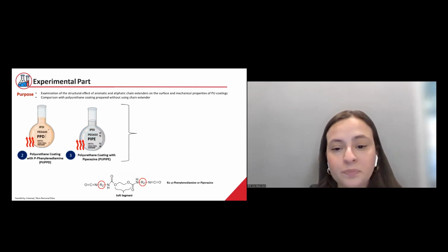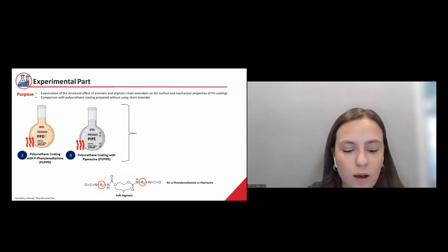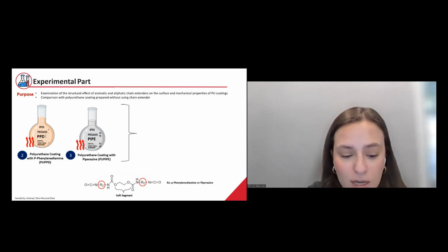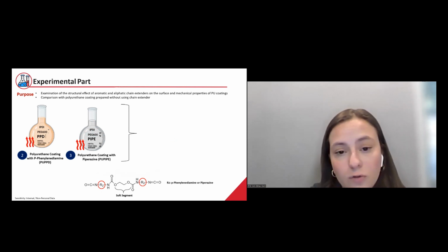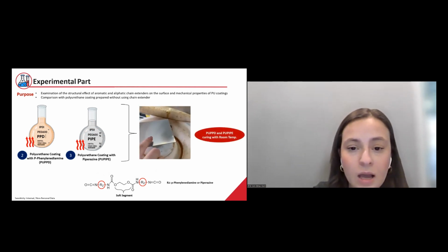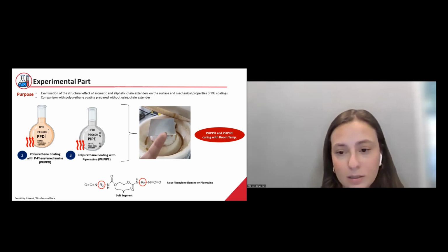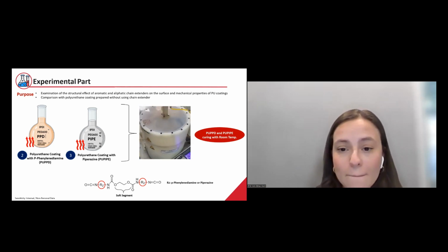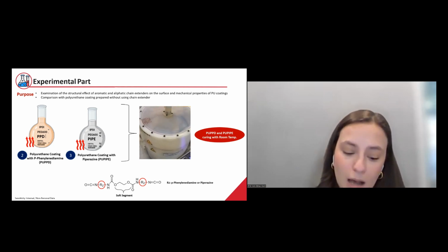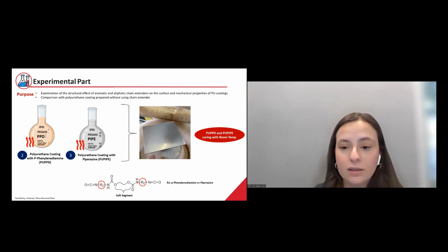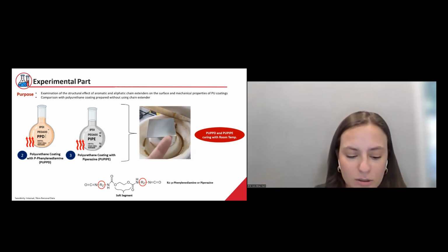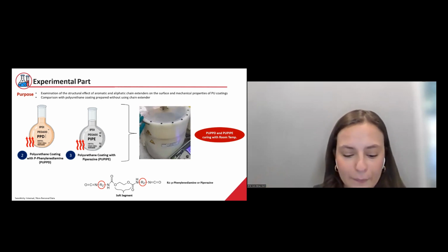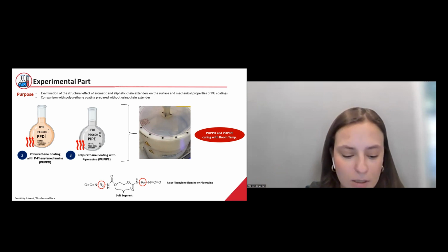130 degrees Celsius. In the other two formulations, we also add chain extenders in the step where we add isocyanate to the solution. We use aromatic paraphenylenediamine and cyclic aliphatic piperazine compounds as chain extenders. Thus, we will examine the effect of compounds with different structures on the coatings. We coat the formulation containing chain extender on the metal surface in the spin coater device in the same way, but this time, coatings cure quickly at room temperature, even right after the application. And as you can see in the GIF, we cure the coatings without any external heat source.